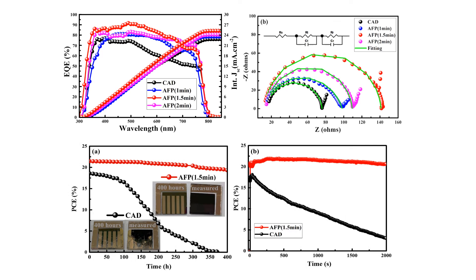We also performed stability analysis. It is a fact that high-quality perovskite films can improve the stability of perovskite solar cells. Here we analyzed stability over 400 hours, and the stability for the anti-solvent fumigation process was notably better compared to conventional anti-solvent dripping, again confirming that these devices were prepared with a high-quality perovskite layer.